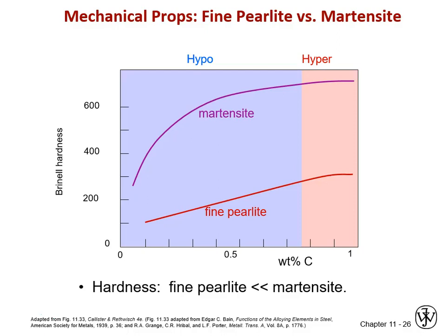And in the case of fine pearlite, if we went the other direction, formed no martensite, we would see the same trend. Obviously, we're going to get a much stronger microstructure with martensite irrespective of the amount of carbon. So going all the way over to a very high carbon steel but not forming martensite isn't going to touch what we can get with martensite irrespective of the amount of carbon. So general rules of thumb: if strength is the big determiner, nothing will be as good as martensite. If you need anything else, you have to start considering other microstructures.